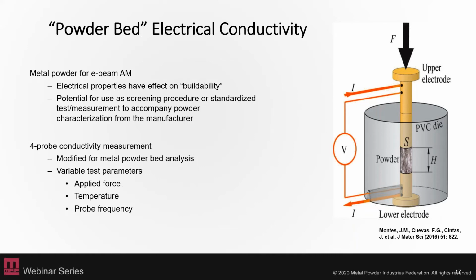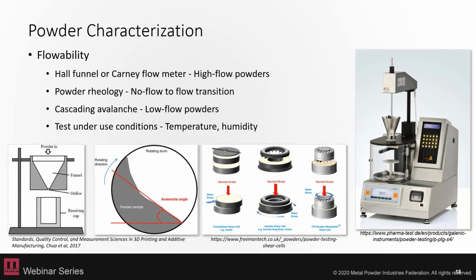Another feature that we've talked about is flowability. Some of the standard methods that have been around for a long time include the Hall funnel or the Carney flow meter for high flow powders. But there are also new methods out there, such as powder rheometers, that give you a no flow to flow transition, or a cascading avalanche for low flow powders, with a rotating drum giving you an avalanche angle as that drum rotates. There are also different flowability measurements based on different use conditions, whether that's temperature or humidity, and that can change your measurements for flowability.